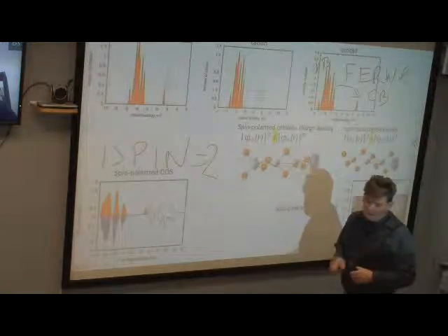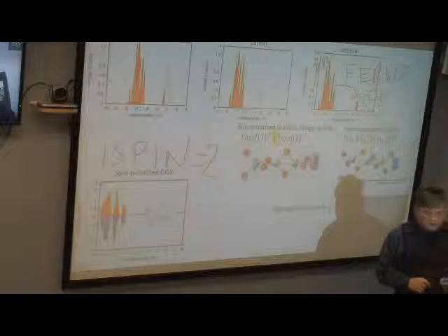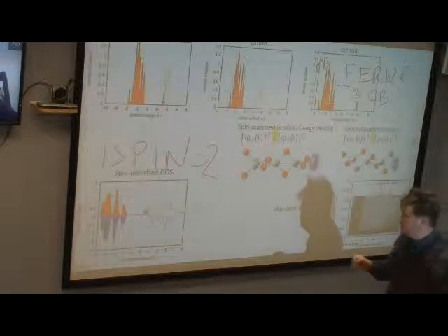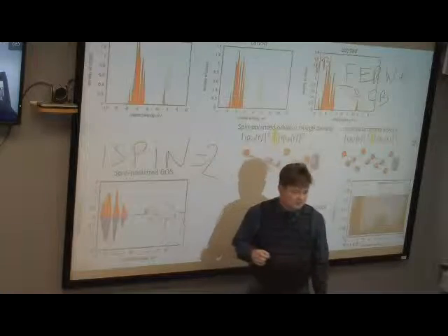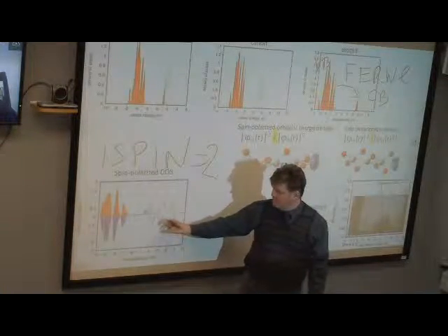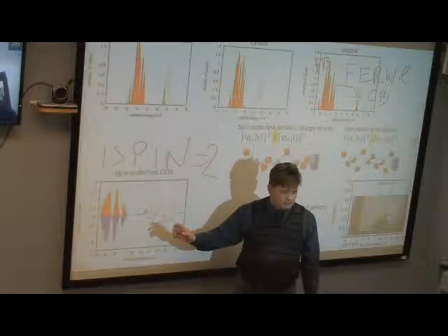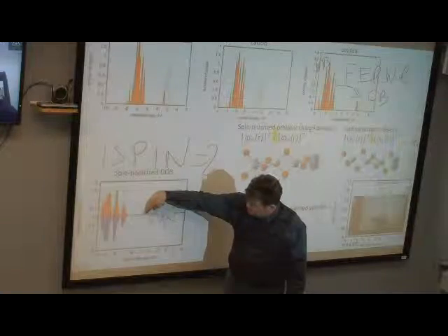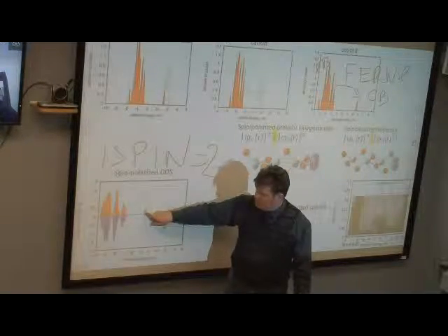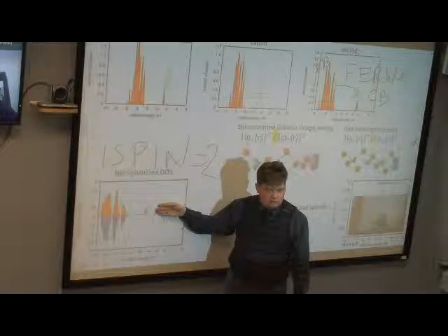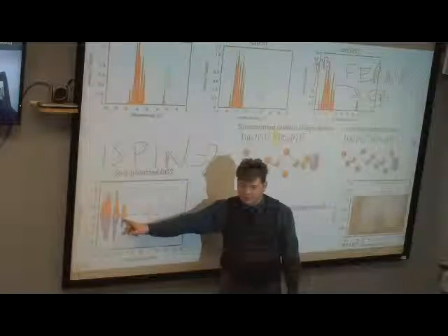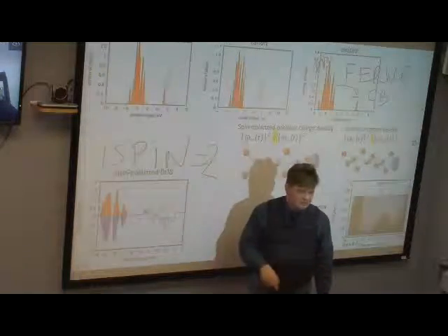And your practical example was a minimalistic titanium dioxide nanowire, where one titanium was substituted with vanadium, which has one more electron. And it is predominantly an open spin, open shell configuration. Number of spins is odd, right? And you do see that in one list of orbitals, there are orbitals that are occupied, but they technically belong to conduction band. And for another spin component, everything is normal. Valence band is occupied, conduction band is unoccupied.